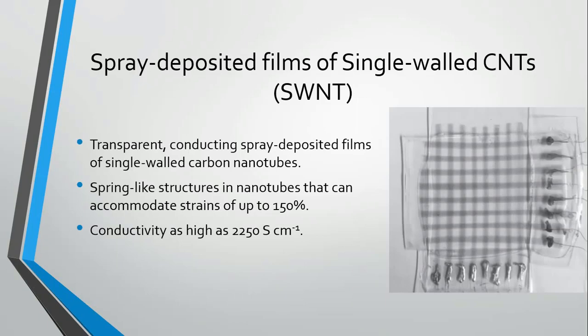Lastly, we have spray deposited films of single walled carbon nanotubes. It consists of transparent and spray deposited single walled CNT films. These spring-like structures can accommodate strains up to 150%. They have conductivity as high as 2250 Siemens per centimeter.